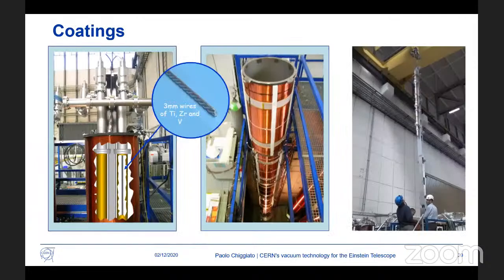Another important line of coating activity is, as I already mentioned, the non-evaporable getter coating. It is a titanium, zirconium, vanadium alloy deposited on the surface of beam pipes. For that, we coated 1,200 vacuum chambers for the LHC, and we continue to coat because we have a change in the layout, so we have to provide the coating for that.